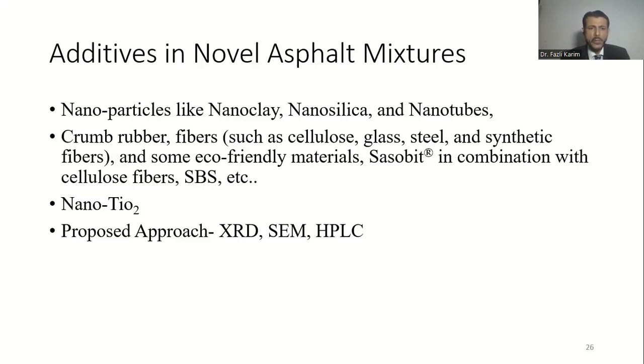Therefore, I personally use nano titanium oxide. Titanium oxide serves multiple purposes. It can either be used in the powder form or it can be melted and used in the liquid form. Number one, it is a catalyst which speeds up the rate of reaction. Number two, it is an antioxidant, which retards the aging process of asphalt. And the most important thing is that it can be used as a tracer. Sometimes when we want to easily detect nanoclay particles or crumb rubber, or the diffusion of crumb rubber when we use it as per wet method in the asphalt mixture, I use TiO2.